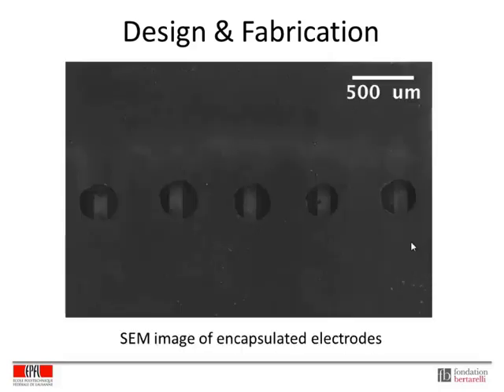So here is an SEM image of the top view of the electrode. The top layer is the PDMS encapsulation with the holes that are exposing the electrode lines underneath. So you can see from this that our alignment is good and our bonding is also good because there's no delamination around the openings.